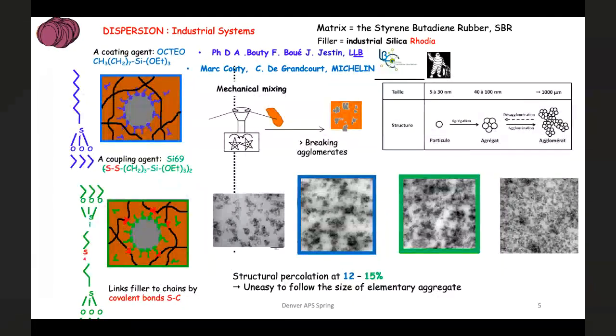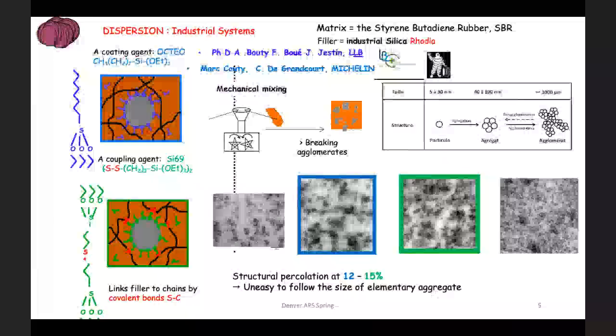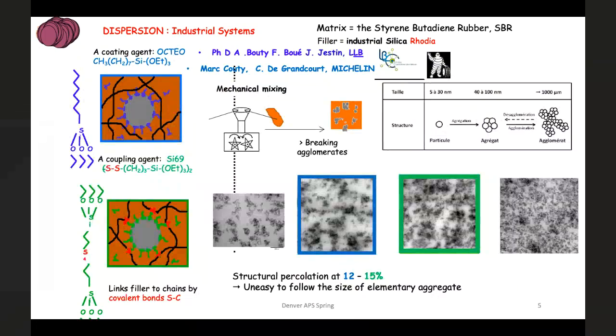Actually, this trick was rather clever, but it was imposing a first step in which the two kinds of chains must have time to mix together, and later on, the system would be very similar to a system in which you have mixed the D and the H chains in solution together with mixing the nanoparticles. Am I clear? Yes. Yeah, thank you. That's pretty interesting for us.